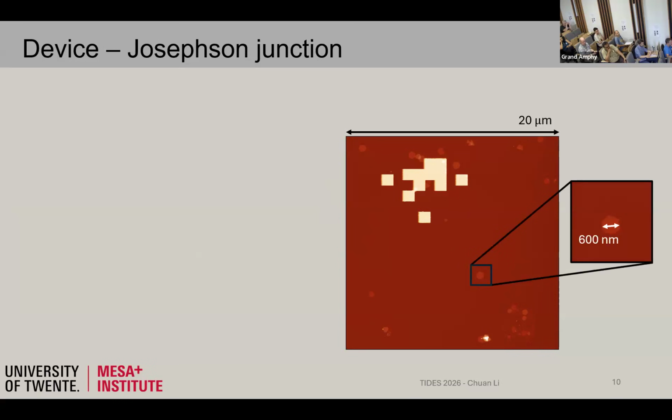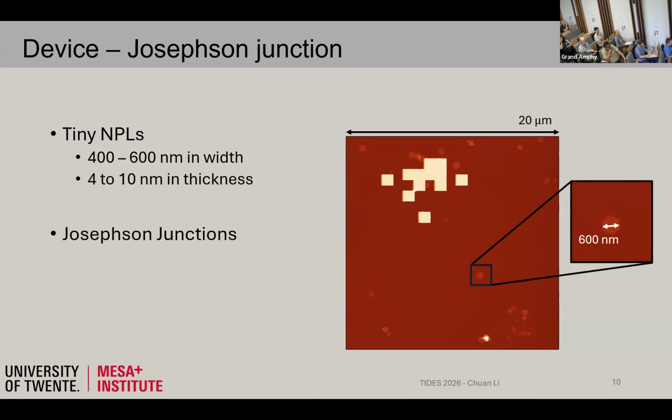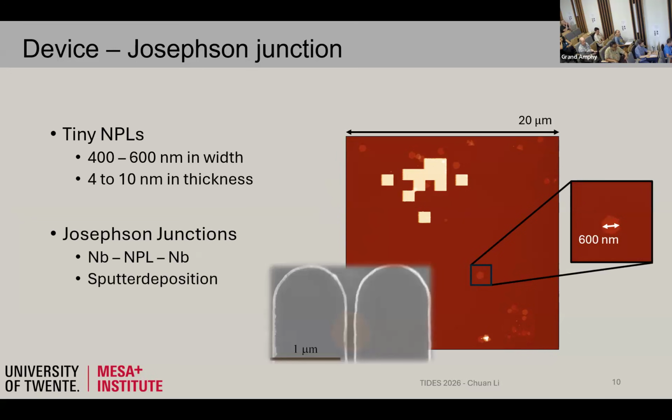The size is typically 600 nanometers, the largest dimension in the material. That's pretty small, but still Feige, our student, is very talented at making these difficult devices, and he managed to contact this flake with two niobium leads and, in the end, induce superconductivity into the system.